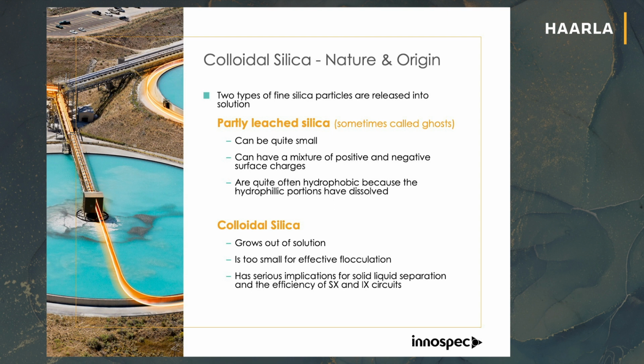So you get the silicic acid formed in solution. That then dissociates, and from dissociation it can polymerize. When you get that, you get the particle growing, and that particle grows out of solution and forms the colloidal silica. The colloidal silica is such a small particle that you can't pull the particles together, so it's very difficult to remove. That's one of the problems we have in the industry, and it has really serious implications, as it says on the slide, in both the solvent extraction and the ion exchange process.